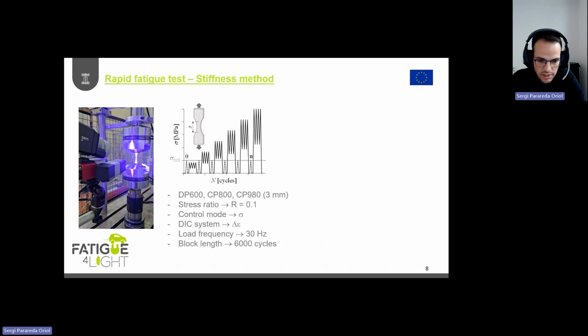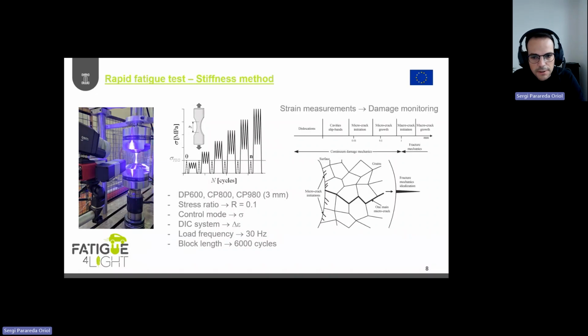So here, just to show the results, we tested 3 different materials: the dual phase material, which can be considered as a reference, and then 2 CP steels, complex phase steels, with a stress ratio of 0.1, controlling the stress. We monitored the strain by using a DIC system that you can see here on the left-hand side of the slide. We used a common load frequency of 30 Hz, a common frequency for an SN curve or staircase testing, and a block length of 6,000 cycles, the length of each one of these fatigue blocks that you can see here in the middle of the slide. Using this strain, we monitored the fatigue damage evolving in the material, and we focused on this first regime, which belongs to continuum damage mechanics.